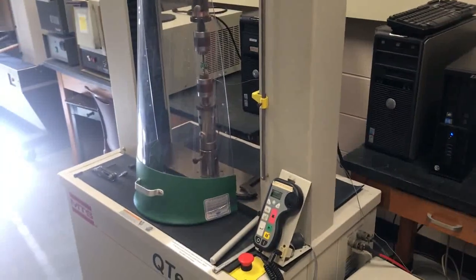The extensometer is in place. Now this is an important point. When we start the test, we have to make sure that as the test progresses, very, very quickly, into, at first, the linear portion of the stress strain, or the elastic portion of the stress strain curve, the extensometer has to be removed before you reach the yield point, or you could damage the extensometer. So what you want to do is start the test, let the test proceed into the elastic portion of the curve very quickly, maybe even after a second or so. You need to pause the test and remove the extensometer, and preserve the data.